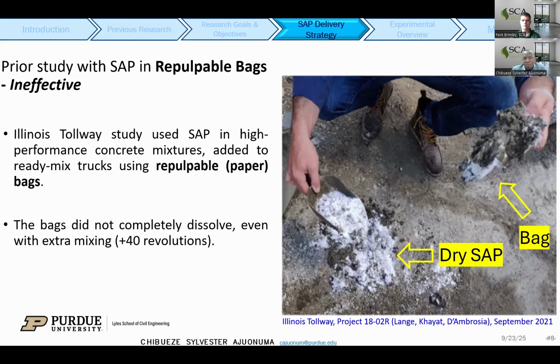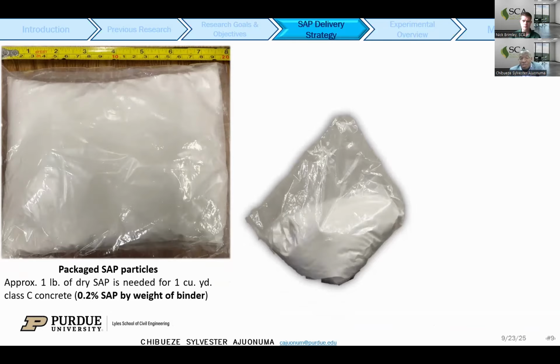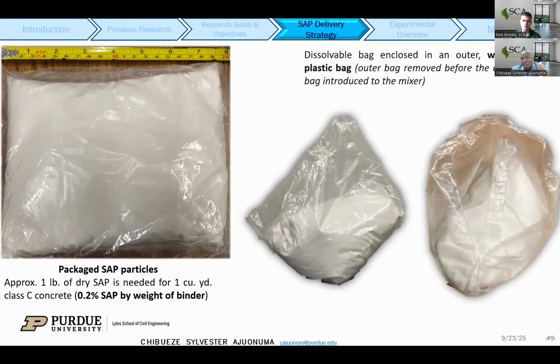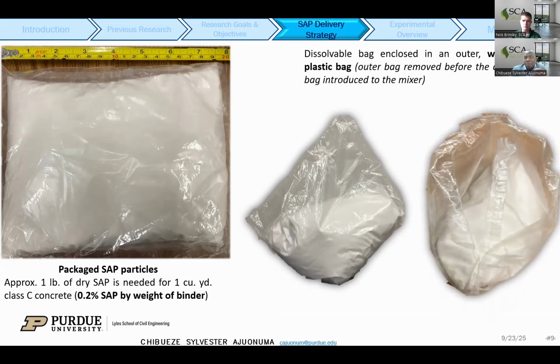So in order to solve this problem, we were able to propose a practical way whereby we use dissolvable bags. The SAPs are repackaged using dissolvable bags, and we found out that approximately 1 pound of dry SAP can be used for 1 cubic yard of concrete, at a rate of 0.2% by weight of the binder. For storage purposes, the dissolvable bag is enclosed in an outer waterproof bag, but usually we open it and then add the dissolvable bag directly into the mixer, and it was very effective.